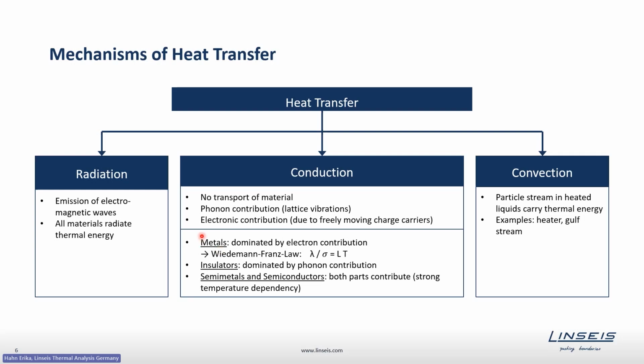One can classify some materials here. For example, in insulators the heat transfer is dominated by phonon contribution. In metals, the electron contribution is dominating heat transfer. We also have this very useful law called the Wiedemann-Franz law, which relates the thermal conductivity to the electrical conductivity, where both of them are connected via the so-called Lorentz factor L and the temperature. For semimetals and semiconductors, both parts, phonon and electronic contribution, transfer the heat. And here one can see that there is a strong temperature dependency, so that in one temperature range maybe the phonon contribution is dominating, and at higher temperatures, for example, the electronic one.